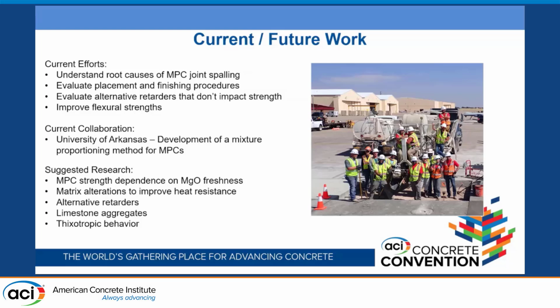So current collaborations are going with one of Cameron's students, Riley. She's helping us develop sort of a 211 style, if you will, method for developing magnesium phosphate concretes. And then suggested research, as I alluded to, is alternative retarders, matrix alterations, strength dependence on MgO freshness. I put limestone aggregates here because early on we decided not to use limestone aggregates because I read that they could be reactive with the sodium phosphates. But we ended up using a potassium phosphate, and he used limestone aggregates throughout his whole project and didn't see any issues. So I'm curious, for the potassium phosphate, if that's even an issue, and then also the thixotropic behavior.